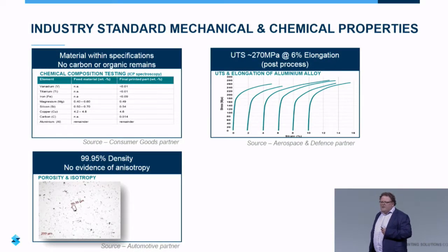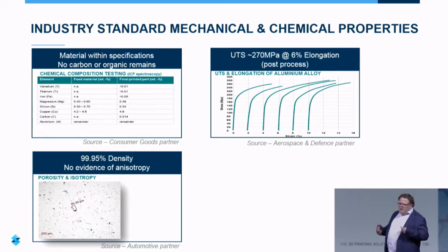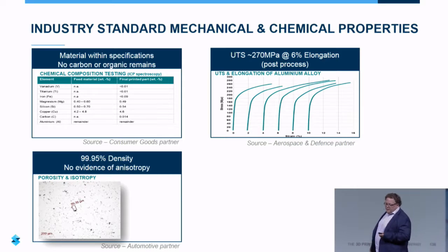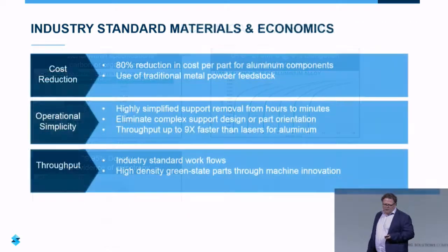Some other key things here, a bit techy, I'm afraid, but it's worth pointing this out to you. The architecture of the technology that we're announcing today: what you put in is what you get out. The chemical composition of the metals that come out of this process is exactly the same as those that go in. There is no percentage of other organic carbon-based material in there. 99.95% density of material. No evidence of anisotropy in that Z-axis. And industry standard mechanical properties, so 270 MPa as an aluminum material. So very common industry standard figures that you would expect from a powder-based aluminum process.